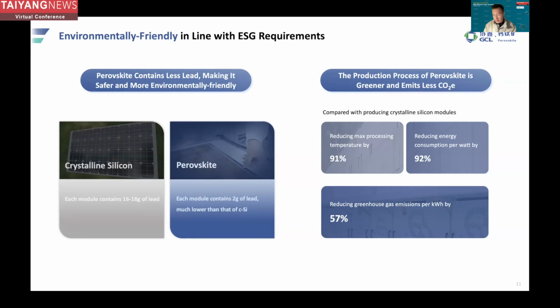We are reducing the usage of lead, and the production process of perovskite is much greener and emits less carbon dioxide. It's simply because the temperature applied is much lower than that of silicon. In a lot of typical procedures for silicon production, the temperature goes as high as 1000 or even 1500 degrees. But for the production of perovskite, the whole procedure is lower than 200 degrees.